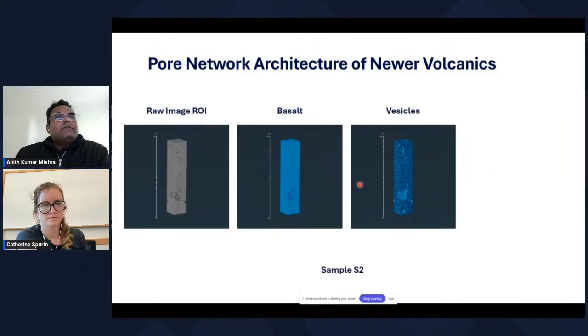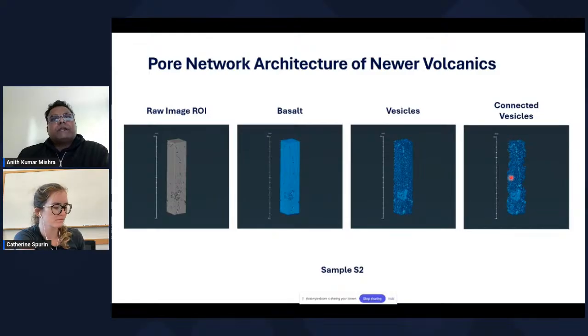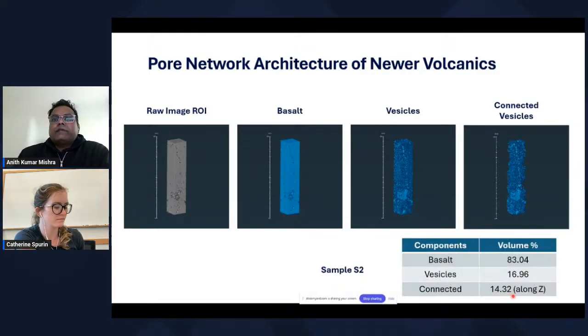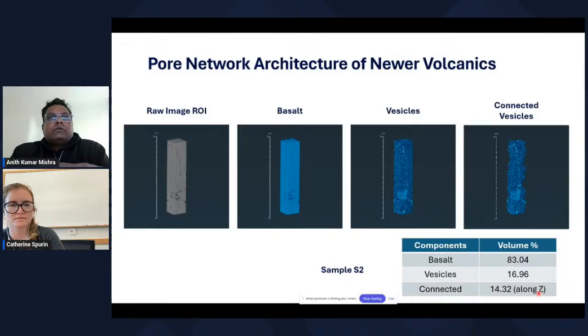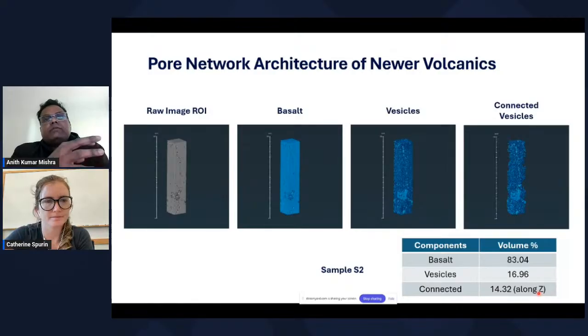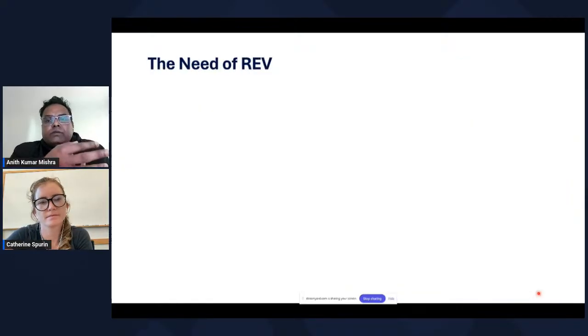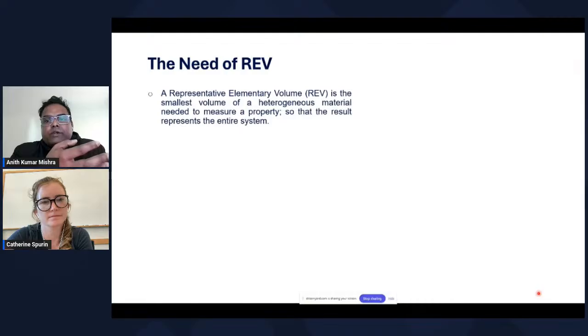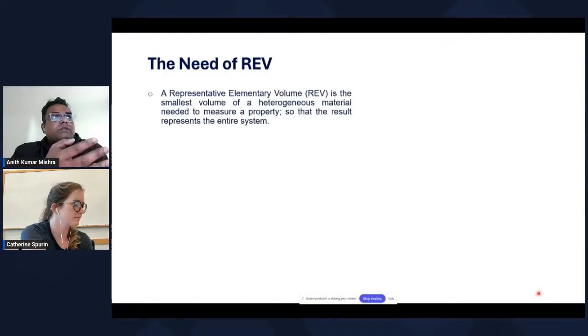For the second one, we did the same, and we found much better connectivity. Here we actually found some connectivity along Z. So with these examples, what we can see is that the pore network and the vesicle structure of basalts is highly heterogeneous in nature. To address this heterogeneity, we need to come up with something called a representative elementary volume. The representative elementary volume is the smallest volume of a heterogeneous material which we need to measure the property on, so that it represents the entire system.